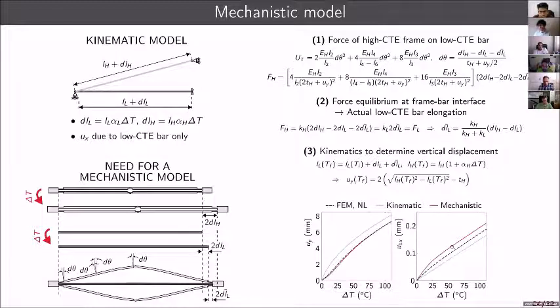We did that, and despite the fact that the horizontal displacement, as you can see from the red lines down here, is still a little bit off, you can see that now we can capture much better the vertical displacement of the cell. And in particular, you can see that this model allows us to capture this double inflection of the response.